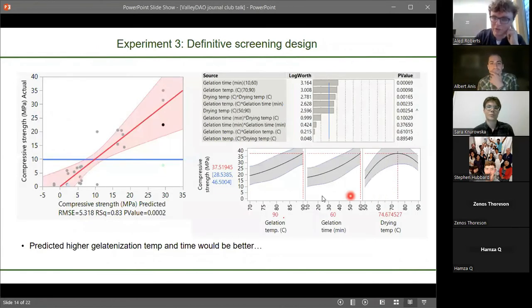And what this experiment showed us was there was a couple of factors which are really important. Basically, the gelation temperature, so the temperature we're gelling at, and the gelation time were set too low. It's like if you're baking a cake, but the oven temperature is too low and the time in the oven is too low, nearly all your cakes are going to not taste good because these factors are just overriding everything. But that was really useful information to find out early without wasting lots of time doing lots of random things, then realizing, oh, the oven's set too low. And it predicted higher gelation temperature and gelation time would make things better. So that's what we did.